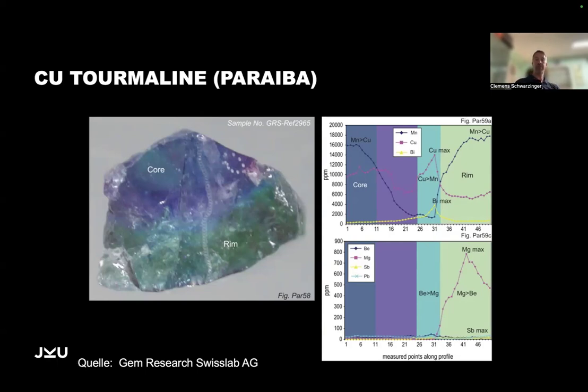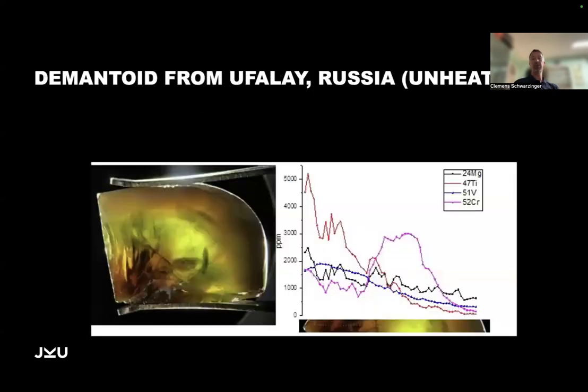What does it help us? This is the good question. Now, we did the same in my lab with demantoid garnet, for example. So demantoid garnet from Russia can be green in its natural state, but it can also have some yellowish and brownish colors. And if you heat treat them, then they turn green. So what we found out is that in the center, we have the highest concentration of titanium. Again, you see here the slides. This is titanium. And then you have this valuable green zone where you have the highest concentration of chromium.